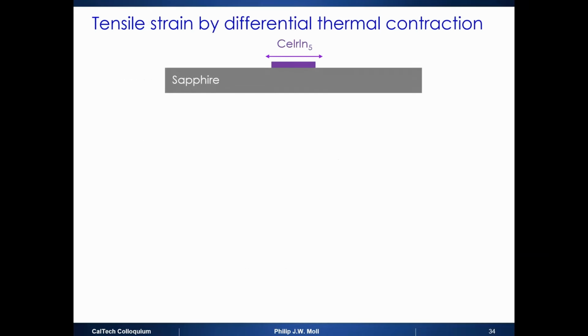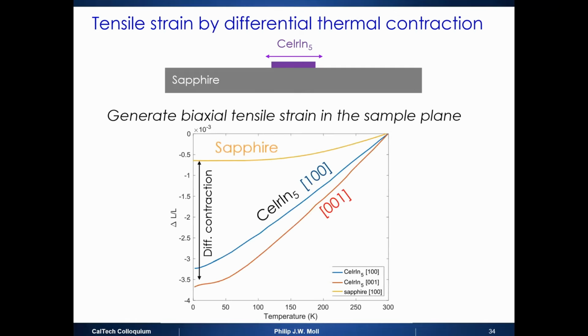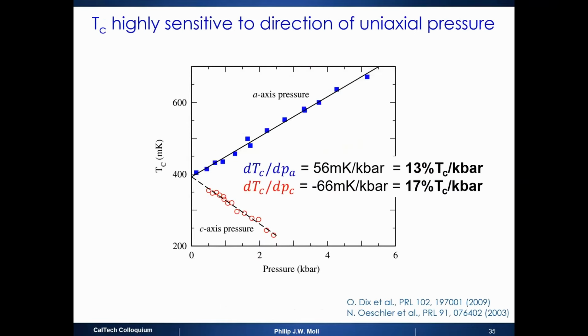So how do we do this? Well, we simply exploit some differential contraction between our slab that we FIB cut and the substrate. In this case, it's sapphire. It has the nice property that it has almost no thermal contraction. So sapphire contracts very little, whereas most cerium 4f, 5f compounds contract like crazy. So this material wants to contract a lot, but it can't because it's rigidly welded. So it will be under a lot of tensile strain. This is how we get tensile strain in, but it will be welded at the surface boundaries. So the boundary condition to the mechanical problem is what you can address with shaping. And that's what we're doing.